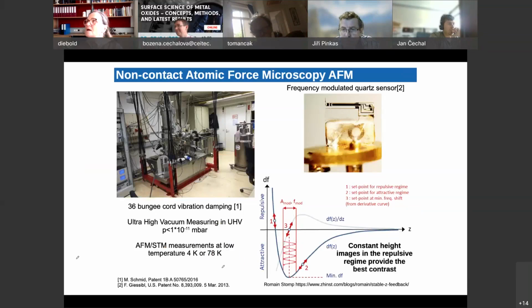Now, as I mentioned in the beginning, we have this non-contact atomic force microscope where we have a harmonic oscillator, which is this tuning fork that swings with its own resonance frequency, typically 20-30 kilohertz. It has a very high quality factor. That means you start swinging and it swings forever. So there's very little damping, which means the resonance frequency is very sharp. We've mounted here an STM tip, a sharp tungsten wire, and we can measure the tunneling current. When one brings the tip close to the sample, one measures the change in resonance frequency.